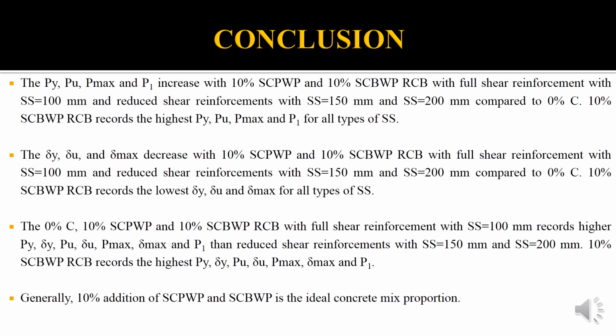10% shredded cardboard waste paper reinforced concrete beam records the lowest DY, DU and DMAX for all types of stirrup spacing. The 0% C, 10% shredded copier waste paper and 10% shredded cardboard waste paper reinforced concrete beams with full shear reinforcement with stirrup spacing 100 mm record higher PY, DY, PU, DU, PMAX, DMAX and P1 than reduced shear reinforcement with stirrup spacing 150 mm and 200 mm. 10% shredded cardboard waste paper reinforced concrete beam records the highest PY, DY, PU, DU, PMAX, DMAX and P1. Generally, 10% addition of shredded copier waste paper and shredded cardboard waste paper is the ideal concrete mix proportion.